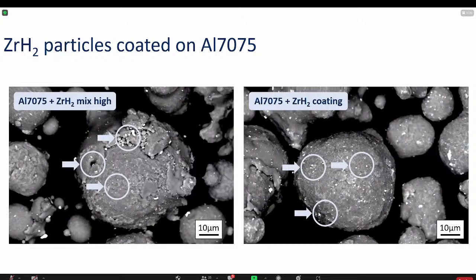Afterwards, I have also analyzed small zirconium particles that are grafted on the powder, which are the particles that we wanted, because they will form some sub-micrometer aluminum-3 zirconium precipitates at the beginning of solidification that will generate grain refinement and so suppress hot cracking. So once again, the coated powder was better because there were more particles on it.